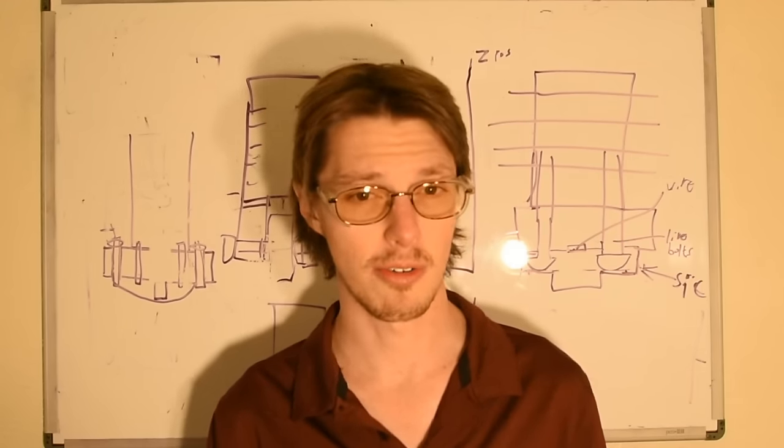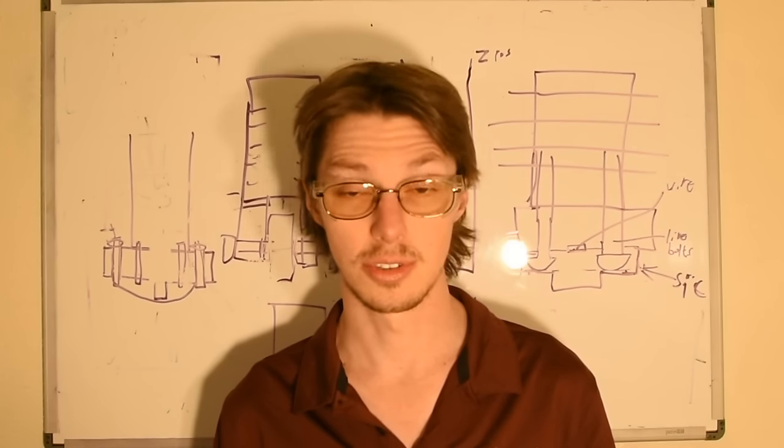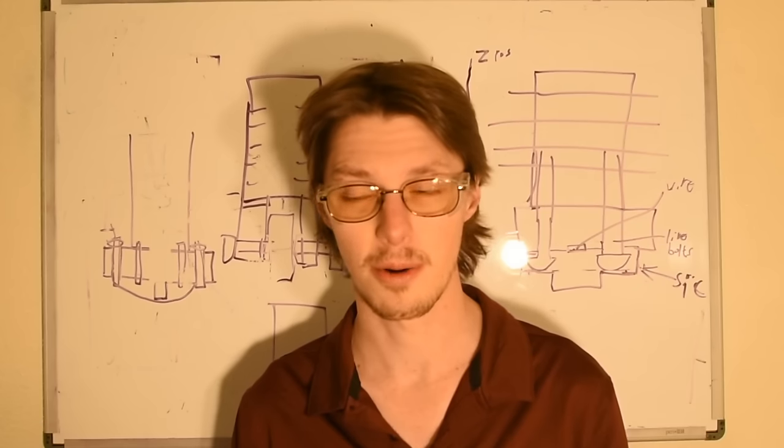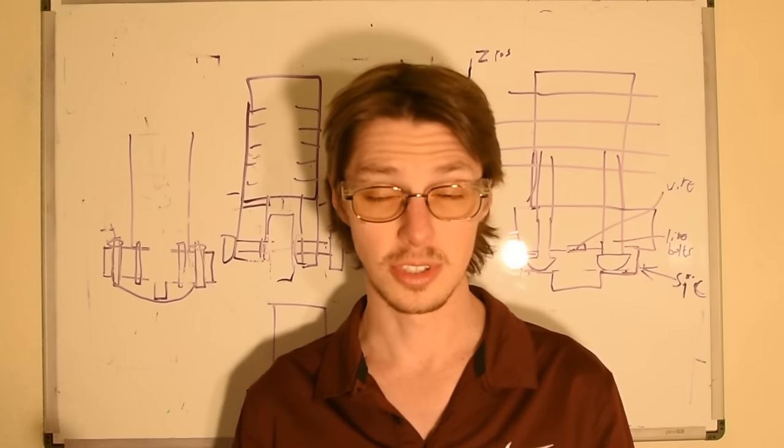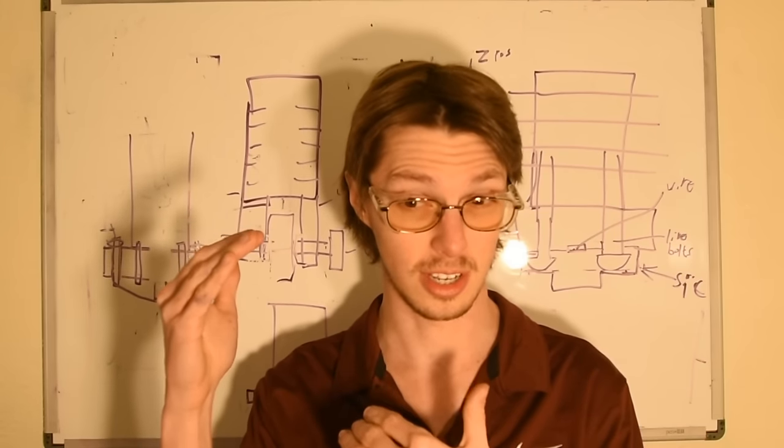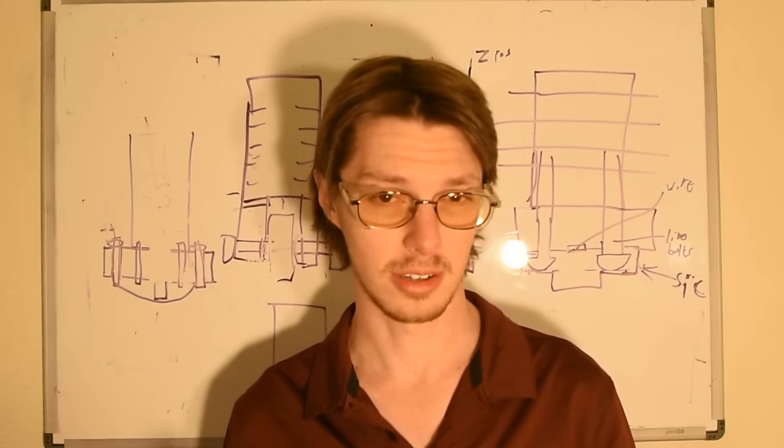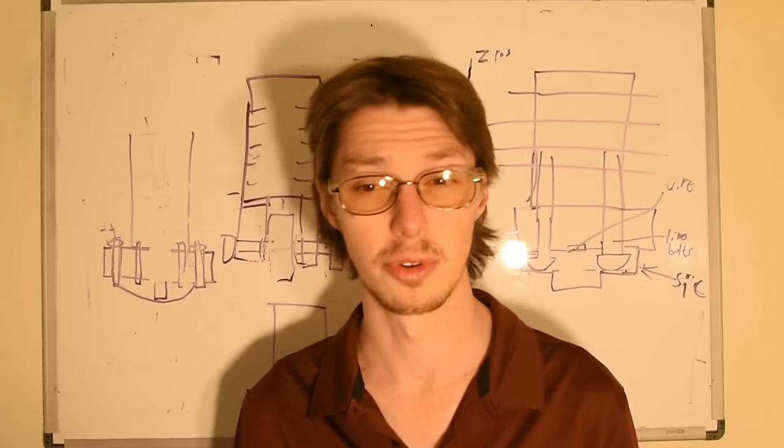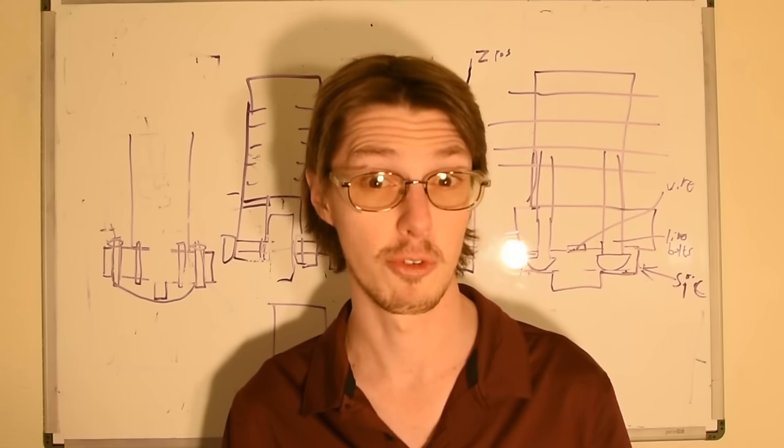So we decided to take an about-face and try a different approach, using just directly heating the wire to the semi-solid state, which is between the solidus and liquidus of the wire. We're using that to make materials alloys with a relatively wide range between the solidus and the liquidus, thixotropic, in other words pasty, make them flowable so that we can actually print with them like you would with clay or chocolate.